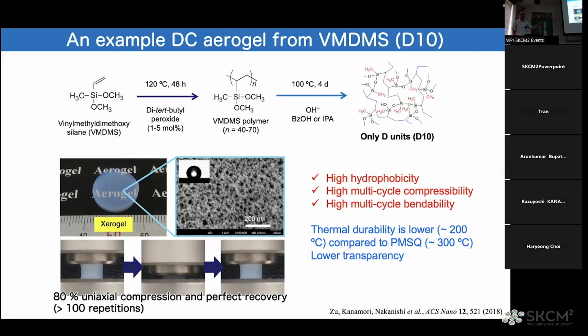And we found that this aerogel consists of both hydrocarbon chains and polysiloxane network. So this aerogel is very mechanically tough. So this is the compression and releasing behavior, not only one time, but we can repeat this process more than 100 times. It is very tough material because of the hydrocarbon chains.